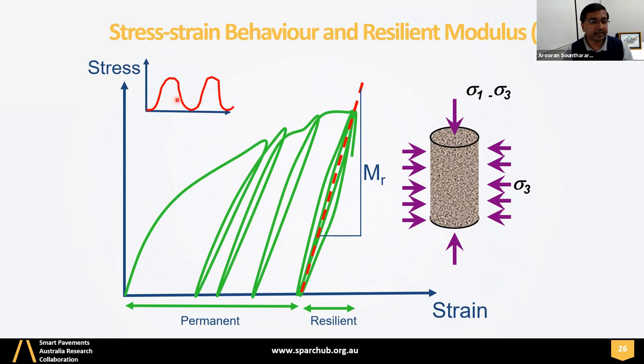And here is the stress. So RLT, this stress is determined based on the application of this material in the field and the expected traffic load or the traffic stress coming onto it. So typically, this RLT stress can range from 300 kilopascal to 750 kilopascal in the triaxial, and they normally use 1 second loading period with 9 second rest period.